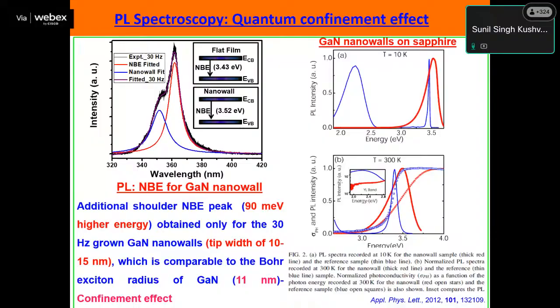People say, what is the advantage of having nanostructures? This is one of the examples, when we are growing gallium nitride nanowall and gallium nitride template. We can clearly see this is the gallium nitride photoluminescence peak, and this is from the nanowall. There is a shift of around 90 meV in the near band edge emission compared to the bulk gallium nitride, and it is mostly coming from the quantum size effect, because the tip width of the nanowall is around 10 to 15 nanometers, which is comparable to the Bohr exciton radius of gallium nitride, that is 11 nanometers. So this is one example. We can see this quantum confinement and quantum size effect even in the gallium nitride nanowalls grown using this laser MBE.